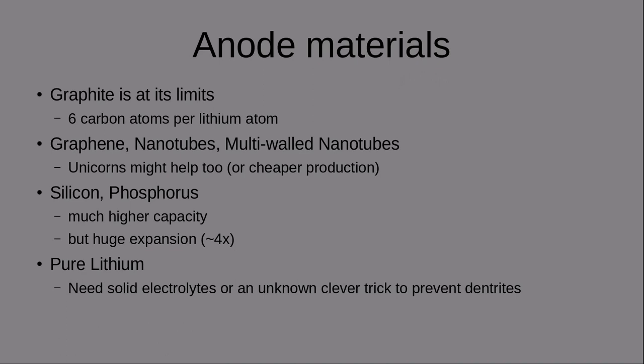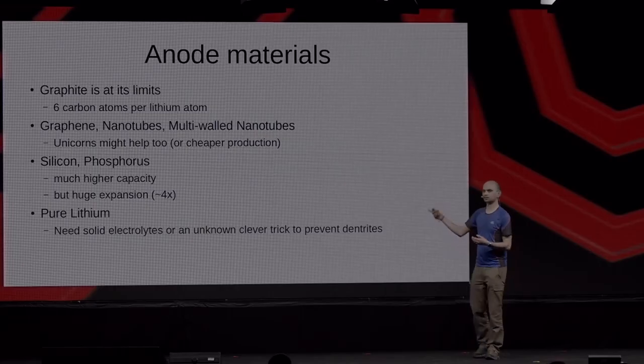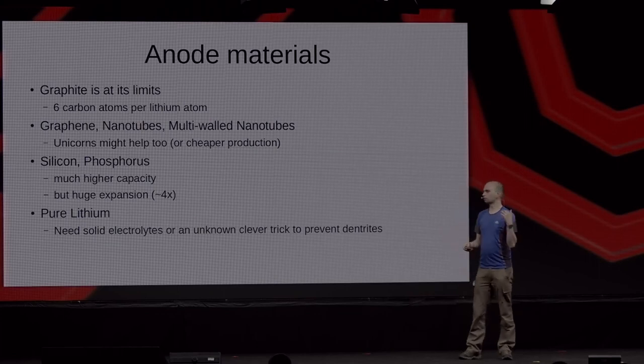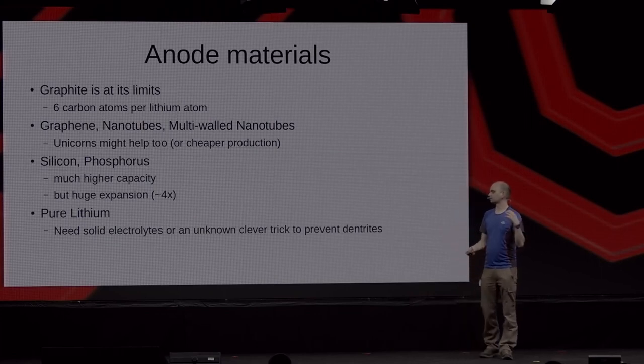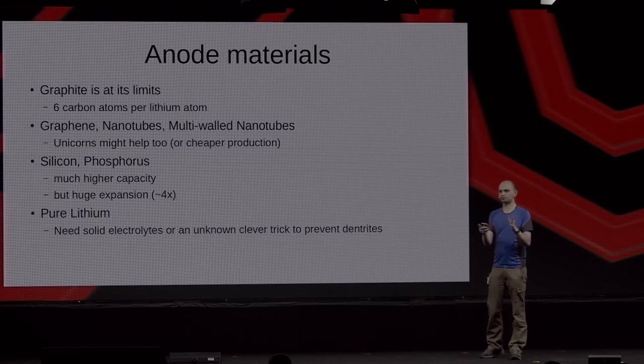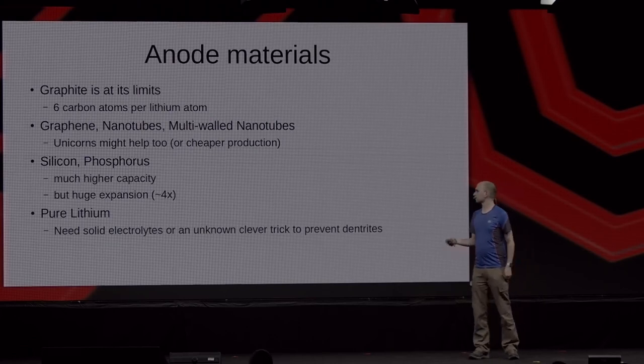The problem is this is about as expensive as gold. Maybe not quite, but almost. And it's not useful for batteries right now. Maybe someday somebody gets to make those on the cheap, and then it's an option. Silicon and phosphorus could help as well. It could improve upon the graphite, have much higher capacities. Because especially silicon forms an alloy with lithium, and you get much better ratios, and so you can get much higher capacity.